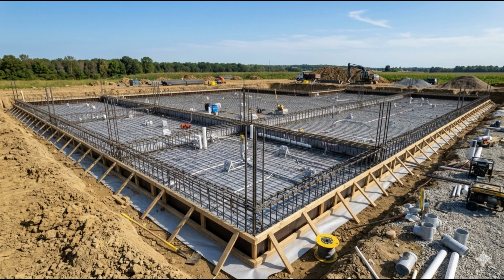Gerald specified S3 slump class, 100 to 150 millimeters, on the assumption that the contractor would use a pump, as was standard practice for a pour of this size. The cement type was to be CEM II/A-LL 42.5N or CEM I 42.5N, which gave the contractor flexibility on cement type while ensuring adequate strength development.